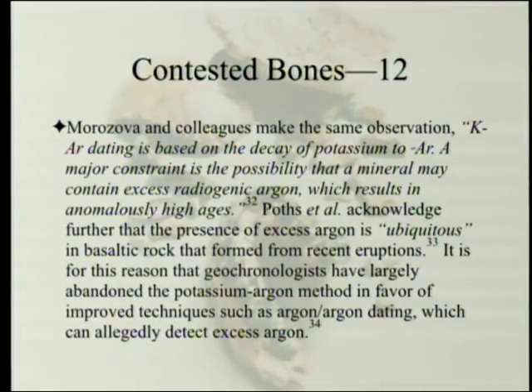Morozova and colleagues make the same observation. Potassium-argon dating is based on the decay of potassium to argon-40. A major constraint is the possibility that a mineral may contain excess radiogenic argon, which results in anomalously high ages. Poths et al. acknowledge further that the presence of excessive argon is ubiquitous in basaltic rock that formed from recent eruptions. It is for this reason that geochronologists have largely abandoned the potassium-argon method in favor of improved techniques such as argon-argon dating, which can allegedly detect excess argon.